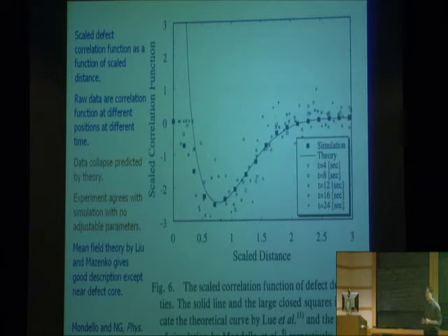This is exactly analogous to what I showed you with the copper manganese alloy, where I showed you the structure factor that the experimentalists measured and then how the data collapsed onto one curve by scaling with the peak wave number. This is exactly the same kind of scaling law, but in this case we're looking at the scaling of topological defects rather than the concentration order parameter.